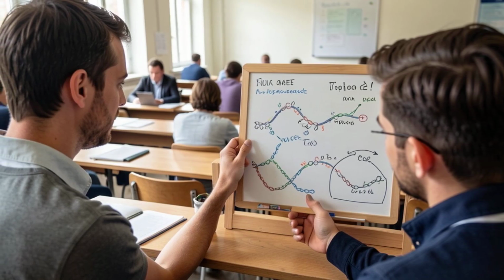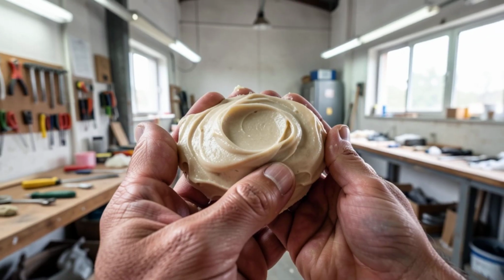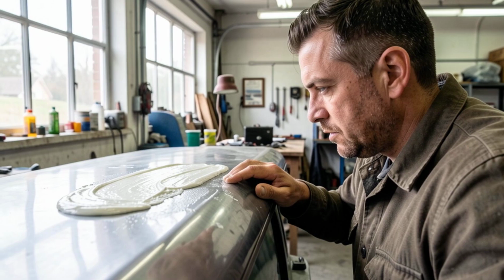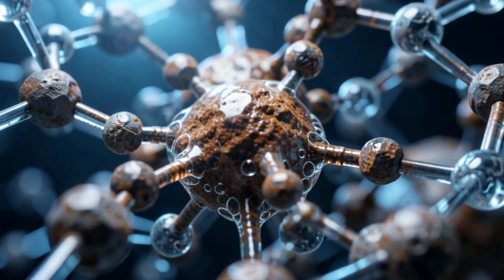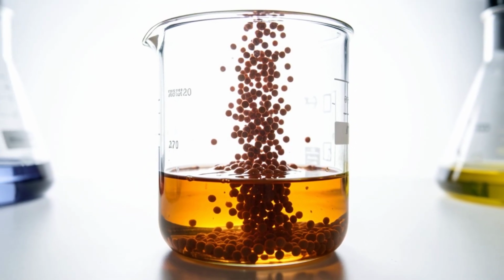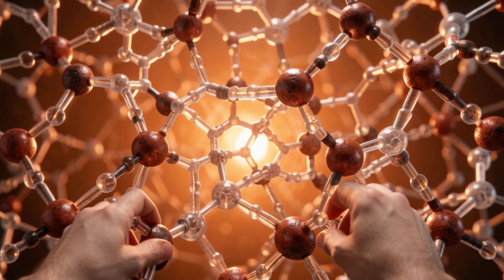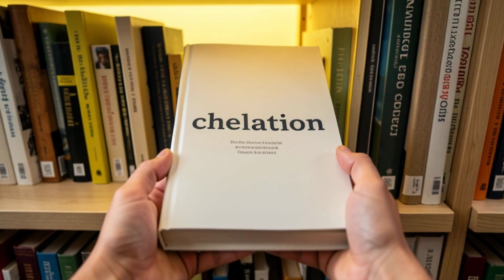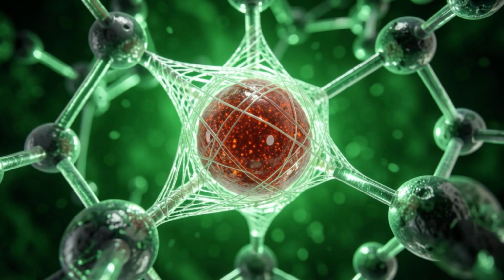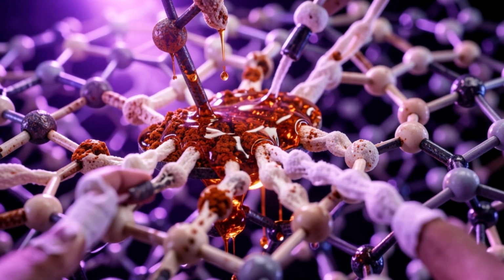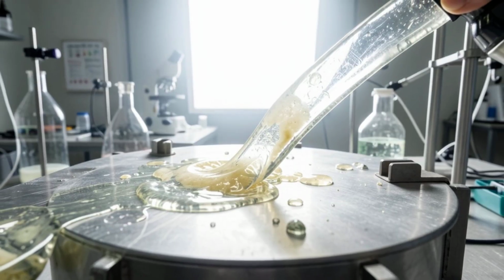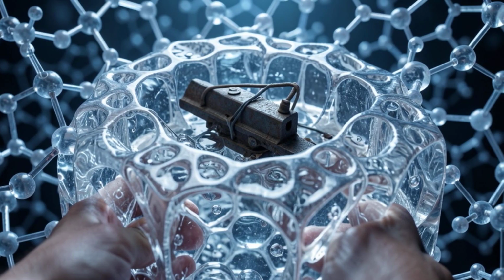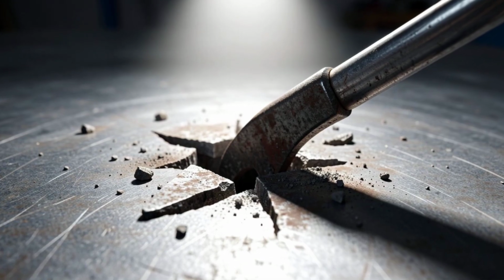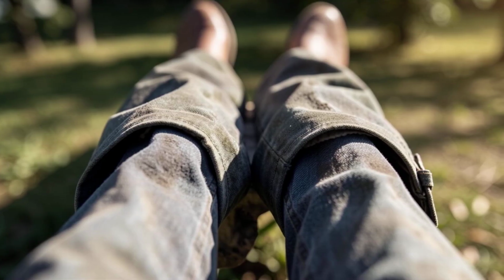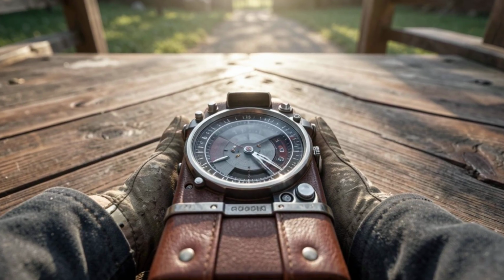Second, and this is the part that makes this paste genuinely extraordinary compared to a simple acid soak, polysaccharide chains have a natural chemical affinity for metal ions. As the acetic acid dissolves the iron oxide and releases iron ions into the solution, the starch polymer chains wrap around those iron ions in a process called chelation. The word chelation comes from the Greek word for claw, and that is precisely what it looks like at a molecular level. The polymer wraps around the dissolved iron ion, locks onto it, and prevents it from reprecipitating back onto the metal surface. As the gel sits on the rust, it is simultaneously dissolving iron oxide with acid and kidnapping the dissolved iron with starch polymers, pulling the contamination away from the metal and trapping it inside the gel matrix where it cannot resettle.